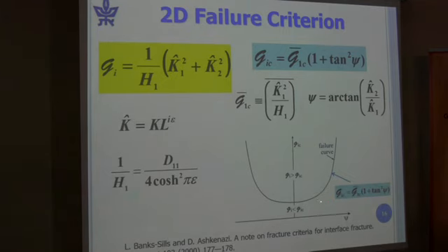You calculate your G1, and if you're above here, that means that you're going to expect failure. And if you're below when you calculate it, that means that you're in a safe zone. So all values below this curve are safe, and all values above this curve indicate failure. And if, let's say, you do something like this for a plane that you're designing, you say, I'm going to have failure, so I better redesign, I better make the part thicker, I better change the geometry in this place in order to be below the curve.